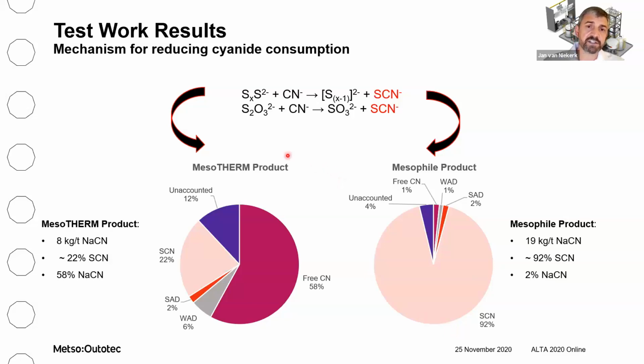Where for the mesotherm product, to achieve the same level of gold recovery, we only needed 8 kilogram per ton of cyanide, with only 22% of the cyanide reporting as thiocyanate, and the bulk of the cyanide still available as free cyanide. So this was really developed to address one of the main operating costs for a BIOX plant being cyanide.